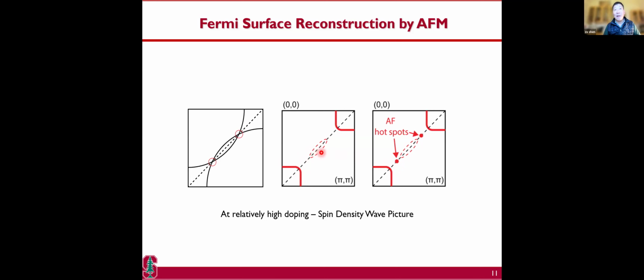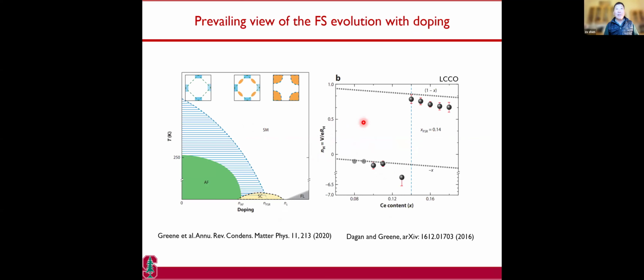Note that there's another piece of Fermi surface inside here, which I put as a dashed line. This one depends on specific doping. It could be a Fermi surface, or this piece could be below the Fermi surface. But the antinode piece is the most robust. Now, this kind of Fermi surface reconstruction has been known in the field for a long time. You start out with the reconstructed Fermi surface, then the hotspot emerges with doping, and eventually you become a large volume Fermi surface.